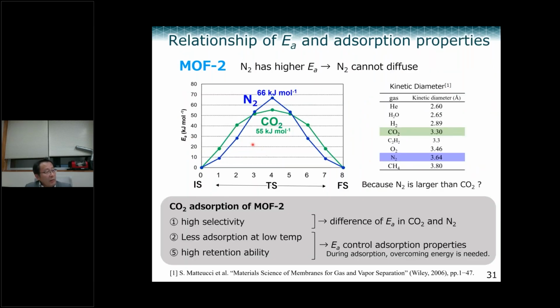Then the next slide summarizes some activation energy results, for CO2 as well as dinitrogen. In the dinitrogen case, the activation energy is 66 kilojoule per mole, which is 11 kilojoule per mole larger than the CO2 activation energy. This is the initial position to another void position, and this is a transition state position. So this activation energy can probably explain why this material shows a very high selectivity for CO2 over dinitrogen.